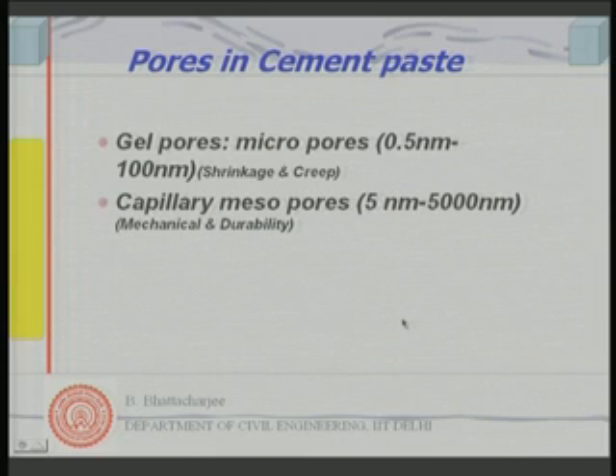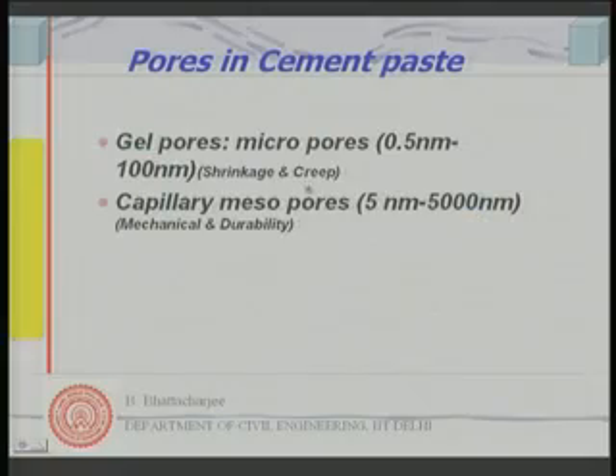Okay. So, what we see is that pores in cement are of two types. Gel pores, which are actually micropores, have sizes ranging from 0.5 nanometer to about 100 nanometer. Then there are capillary pores, which I can call mesopores, and their sizes range from 5 nanometer to 5000 nanometer. We shall see later that the gel pores are responsible for shrinkage and creep of concrete, whereas the capillary pores, which are larger in size, are responsible for mechanical and durability properties of concrete, right. So, these are the sizes of the two types of pores we have seen.